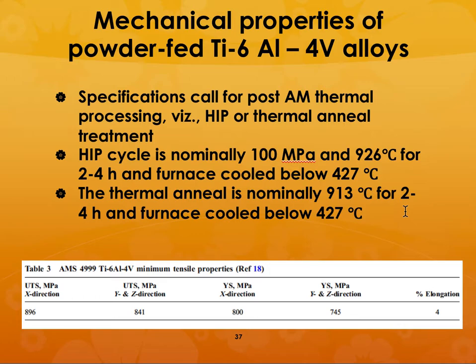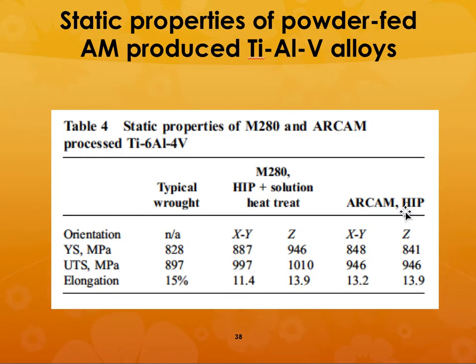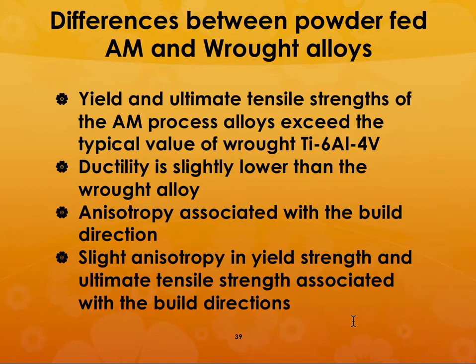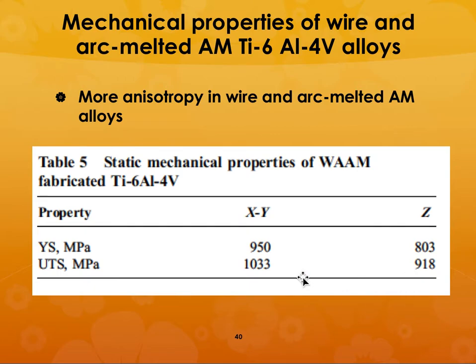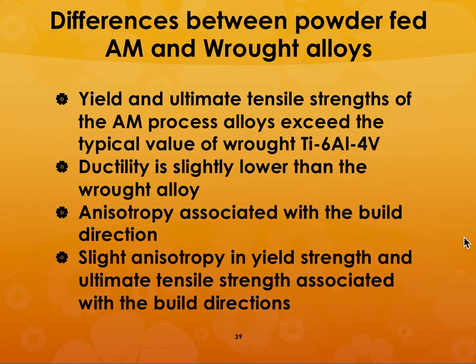You may also do thermal annealing so that any kind of anisotropy in the microstructure can be eliminated. So here are some powder fed systems, you can see that these properties are reasonably uniform in all different directions. But the wire and arc-melted system, and let me come back to this, there is more anisotropy in the different directions as a result of additive manufacturing.